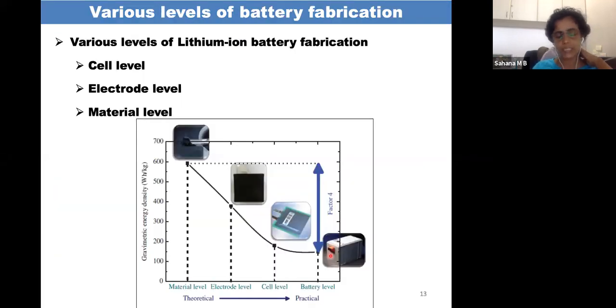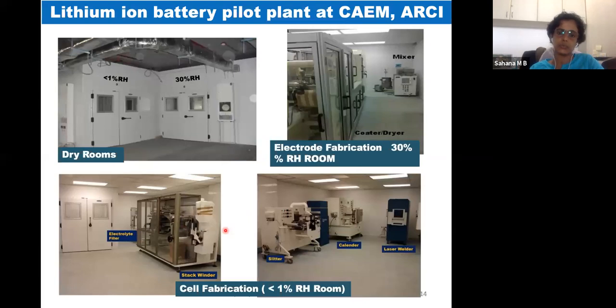So now how to handle these materials? Unfortunately, all lithium ion battery materials, the active materials and the electrolytes, are extremely sensitive to moisture. And once the cells are fabricated, the electrolyte is very sensitive to oxygen also. So all these cells have to be fabricated in a controlled humidity room. The relative humidity should be less than 30% for electrode fabrication, and it should be less than 1% for a cell to be fabricated. Now these are a few of the instruments that are required to get a lithium ion cell.